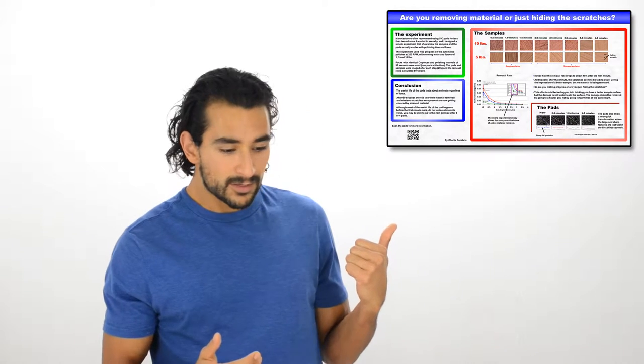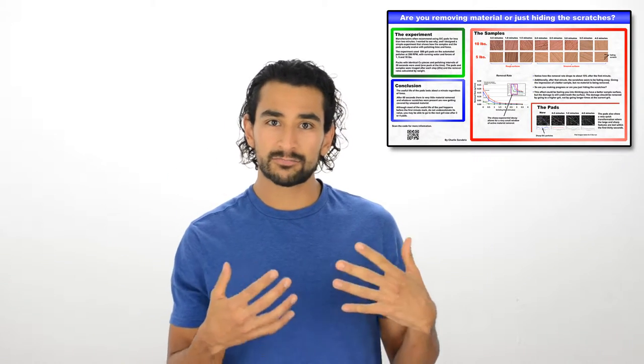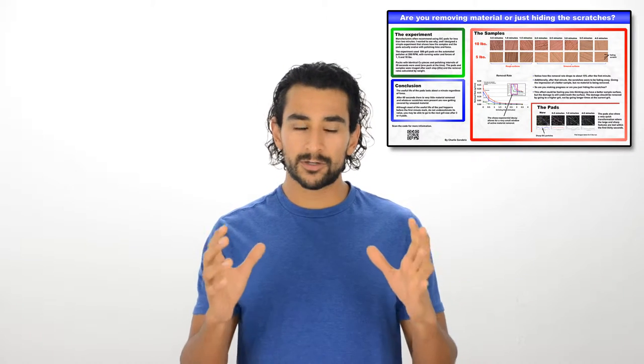So I made this little poster where I perform a little experiment to explore silicon carbide pads a little more. You see, I've talked to Buehler and ACTEC representatives and they've all told me that you should use these pads for very little time. And when they told me this, I thought, of course they'll say that, that means we'll buy more. But once I did the experiment to see if this was true or not, it turns out they're right. Silicon carbide pads only last for about a minute, at the most a minute and a half. And this poster is evidence for that. However, just because they last very little doesn't mean they're not effective. So let me walk you through the poster so we can see what I mean by that.